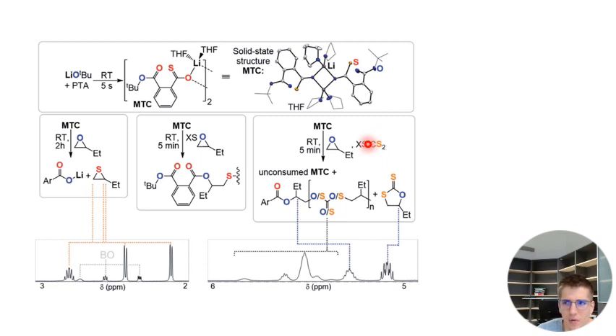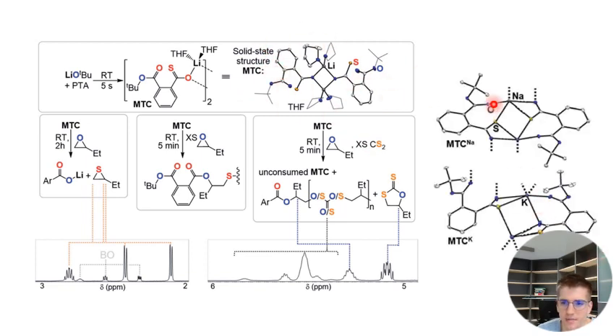But what was perhaps more interesting is that when you made this species with potassium and sodium, these are now softer metals, and the crystal structures then showed that the sulfur also coordinated to the sodium or to the potassium, right? In lithium, the sulfur is nice and free, and so to say ready to then attack a new monomer and propagate, right? Whereas for sodium and potassium, you got some network structures that crystallized out.